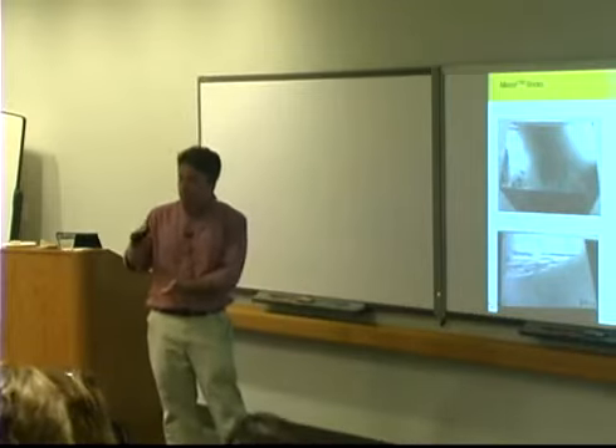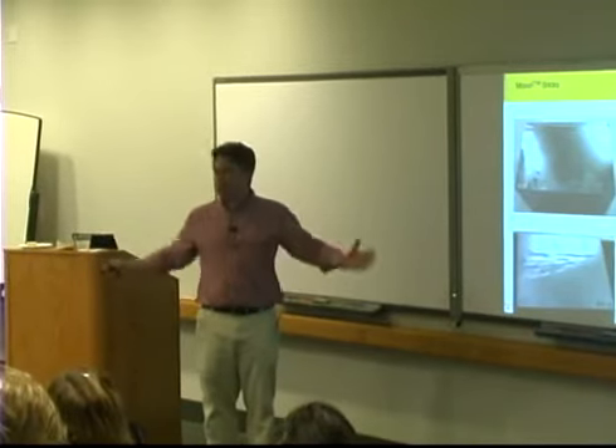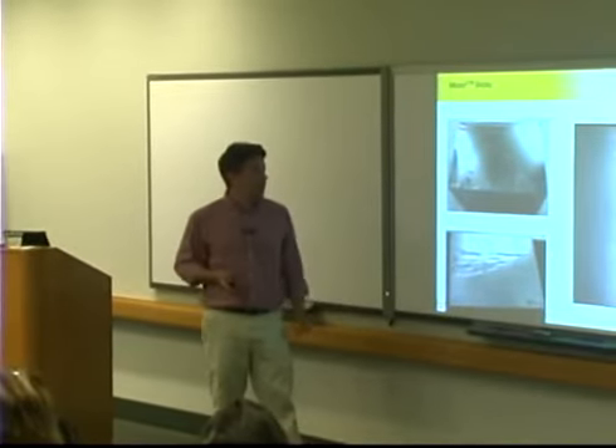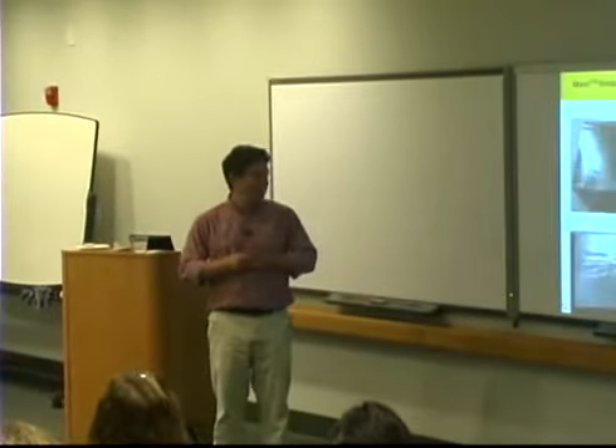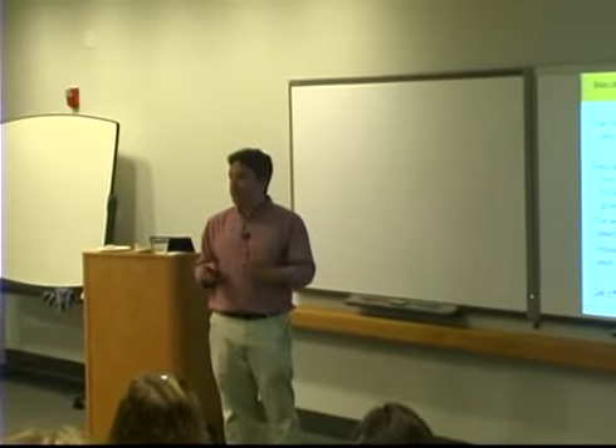But the good thing we've got going is instead of growing a 2 meter long crystal, we're just trying to grow a third of a meter or something like this. And then we're done. And we've grown 25 of these things in parallel. So we can tolerate this to some extent in a way that CZ can't. All right. So the bottom line is that this material gives you a cell efficiency entitlement. And you can, with the right cell process, go from something that would normally be 16% efficient up to something that's even 19 or 20% efficient from a solar cell point of view. And that's really a big deal in photovoltaics.